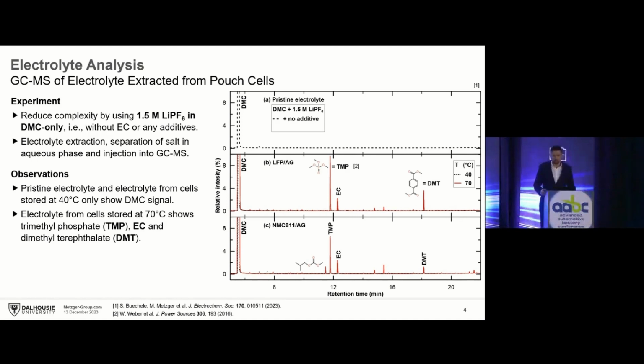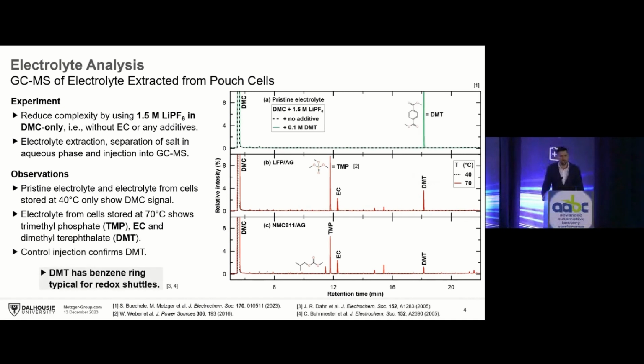In fact, you can buy that molecule commercially, and we did a control injection just to prove that this is truly the molecule that we generate in our battery cells. Sure enough, it shows up at the same retention time, so we're very convinced that this is indeed formed in our cells. And when you look through the literature, you find that a lot of so-called redox shuttle molecules have this benzene ring structure. A redox shuttle, of course, is a mobile species in the electrolyte which can shuttle charge between the positive and the negative electrode. So that could explain the self-discharge we were seeing. That's our candidate for what's causing the self-discharge in our batteries.